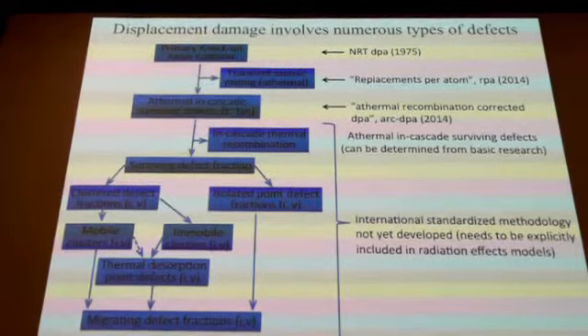It didn't even attempt to talk about this rapid interatomic mixing that occurs in displacement cascades, and didn't correctly account for the recombination that occurs within this energetic mixing effect. So the new international standard, if you will, is trying to address this first part. There are lots of other boxes in this chart that I'm not even going to talk about, that we've recognized for at least the last 15 years as additional complexities that we should have, but this committee decided that trying to tackle all of this in one fell swoop was going to be too much, so we're going to first start out by getting us at least a little bit further down this logic chart.